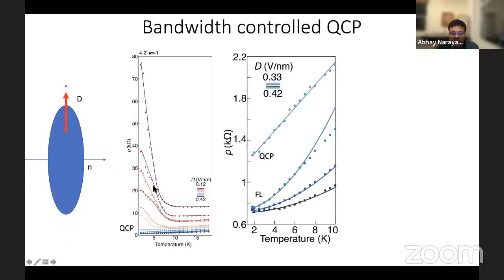Finally, one last thing is everything that I told you about so far is as a function of density, but you can do the same experiment as a function of electric field. And if you do, the result is fairly similar. You can see that there's a region where the sample shows insulating behavior at low temperature, and then there's a region where the sample is metallic. And if I look at the interface between the insulator and the metal, you indeed see T-linear behavior. At the time we took the data, we were not looking for this effect, which is why we did not take as many data points as we should have. We are now repeating these experiments, taking better data. But you can reasonably well see that there's a T-linear behavior at that quantum critical point driven by electric field. And if I go further into the metallic phase, I see once again metallic behavior with T-squared dependence.